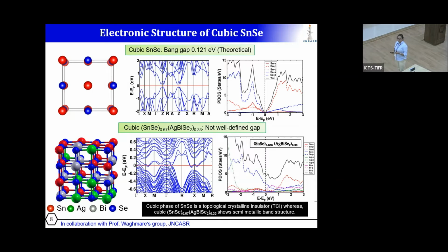And from the Z2 topological index and mirror Chern number calculation, it has been predicted to be a topological crystalline insulator. Whereas the 30 mole% alloyed cubic SnSe system shows a semi-metallic band structure and does not contain any topological properties.